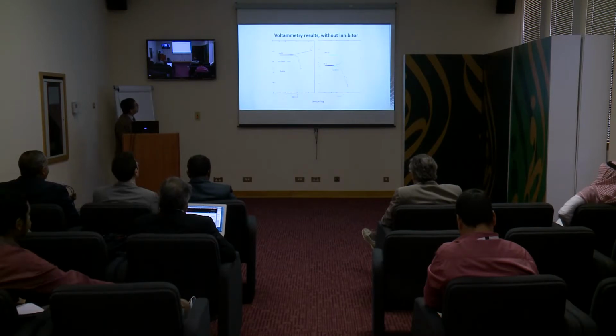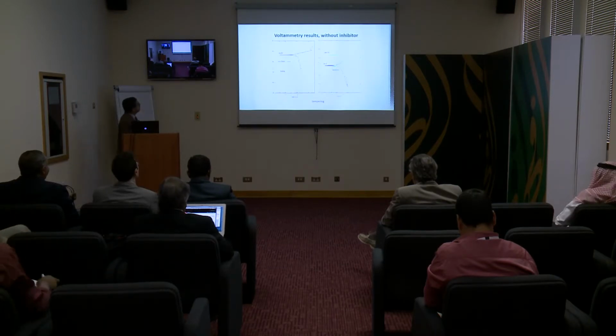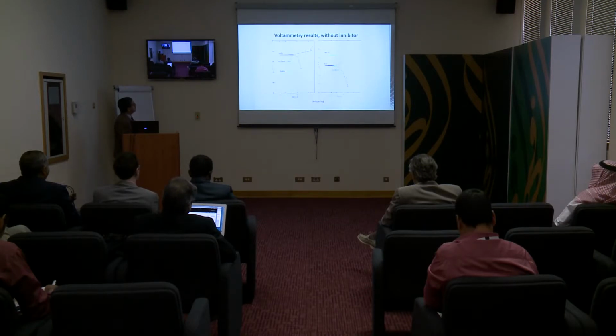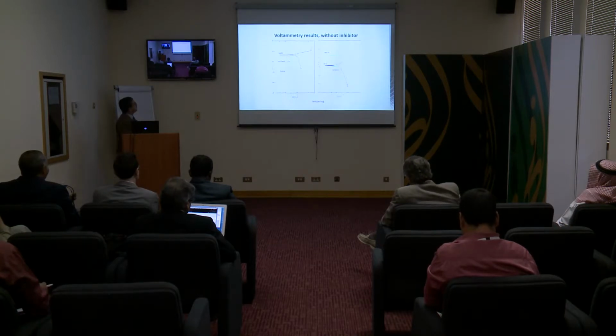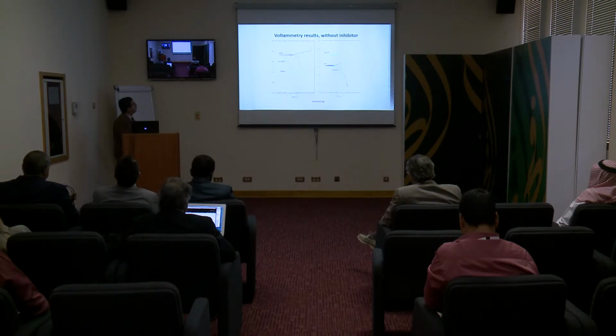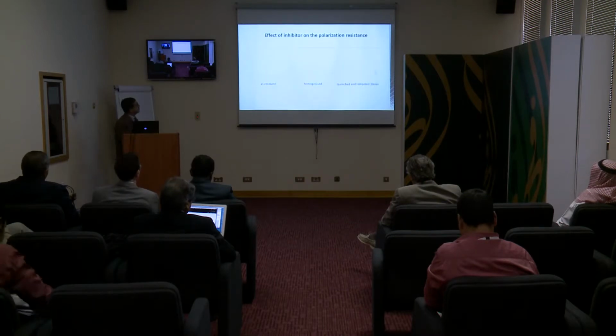I come back here. We can compare the voltammetric behavior of the hard martensite with the treatment of tempering, which gives better behavior by a lower corrosion potential and a lower rate of corrosion. That's about voltammetry.